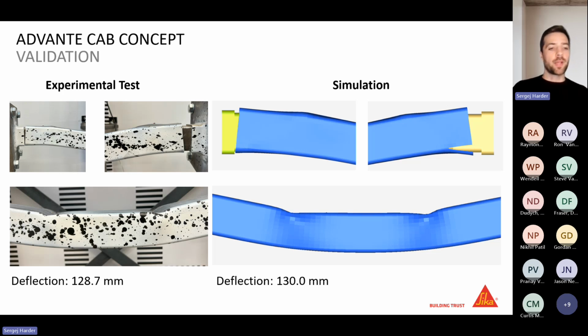And also maybe as a background, we also support a lot of automotive customers there. These crash simulations are quite standard, you could say. And there, these cohesive zone elements or the simulation of adhesives is quite well, you could say, state of the art, and it works very well. So we're not very surprised that it worked well here as well. But yeah, still less than 10% off. That's always my rule of thumb, you could say, to be precise with my model.